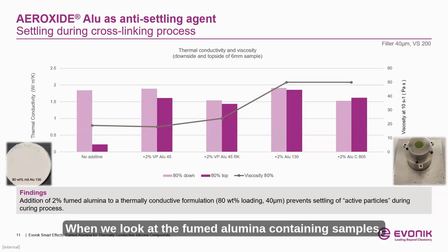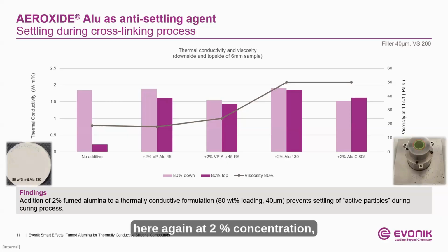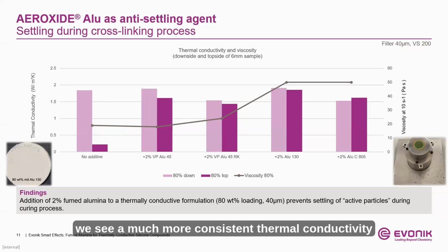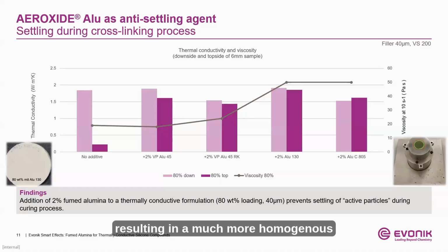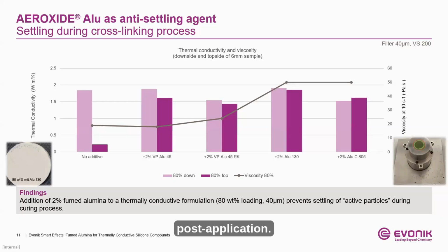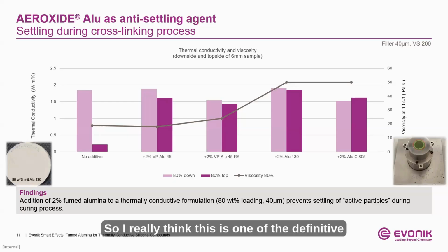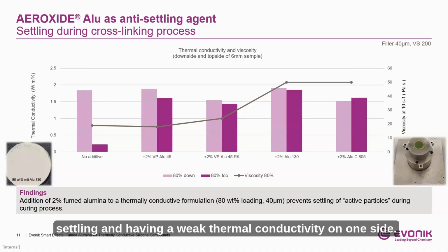When we look at the fumed alumina containing samples used here again at 2% concentration, we see a much more consistent thermal conductivity across both sides of the disk, showing that the high rate of settling of the spherical alumina blank has largely been controlled by the addition of fumed alumina, resulting in a much more homogeneous cured silicone compound post application. So I really think this is one of the definitive slides if you have to take something away here. We've seen the anti-sedimentation benefits. Again, you're seeing them here showcased pretty well in terms of maintaining that thermal conductivity across the entire surface of the cured adhesive rather than just having that settling and having a weak thermal conductivity on one side.